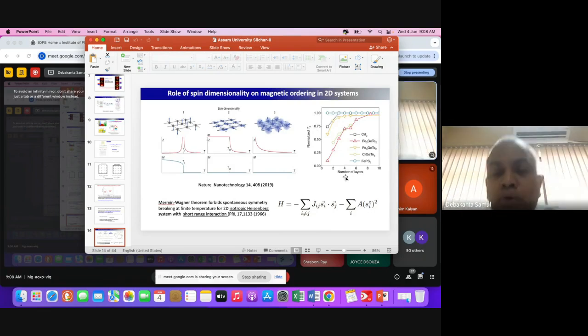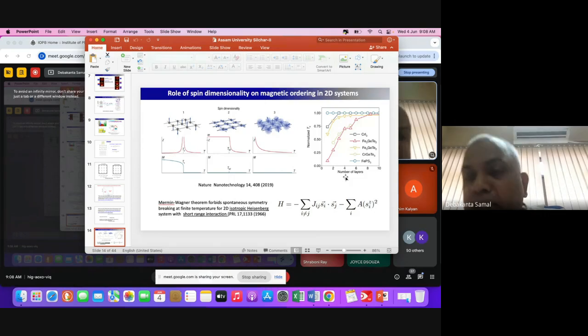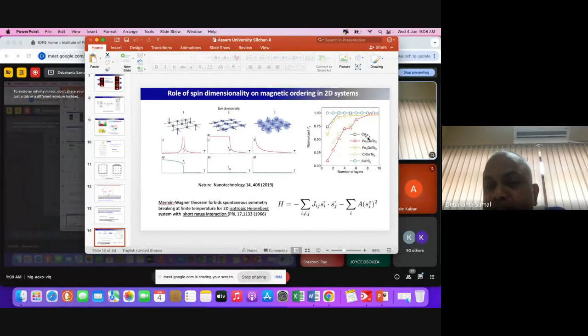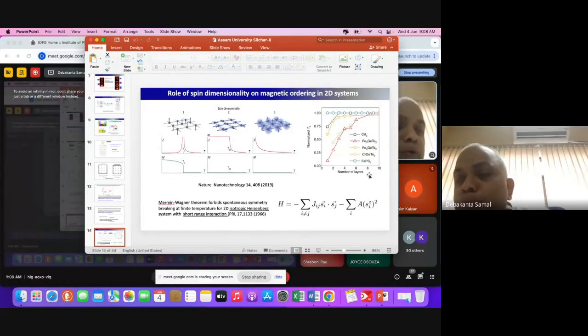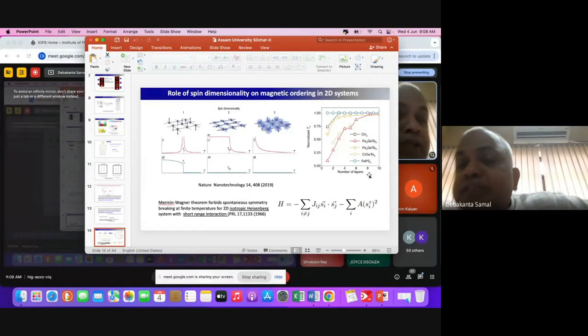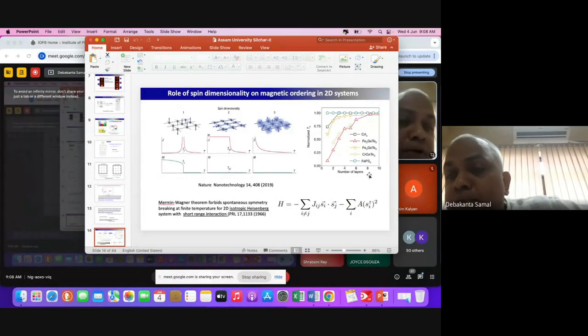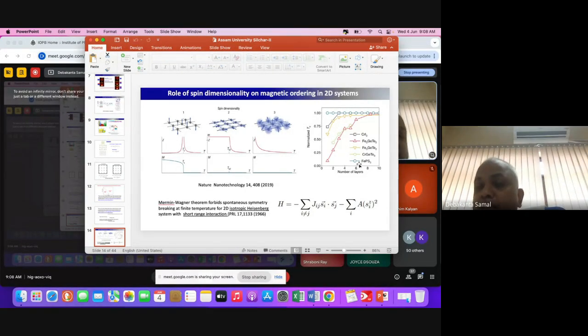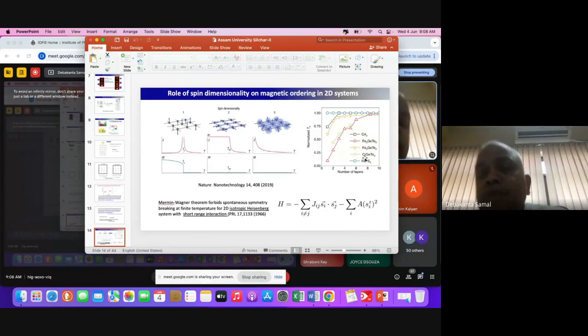But what you see here, there have been many examples in recent days. Just a few years ago, people made 2-dimensional lattices of various materials, starting from CrI3, various magnetic materials. What they see is that even though you put them in a 2-dimensional lattice, they show a phase transition, which does not agree with the Mermin-Wagner theorem, which said that a 2-dimensional lattice with isotropic Heisenberg exchange interaction will not show any magnetic ordering. But here we see clear experimental evidence that there is a phase transition, so ferromagnetism is occurring. So why does it happen?